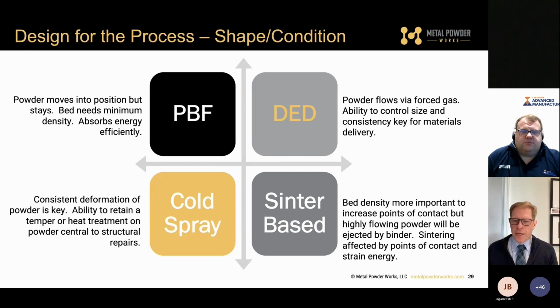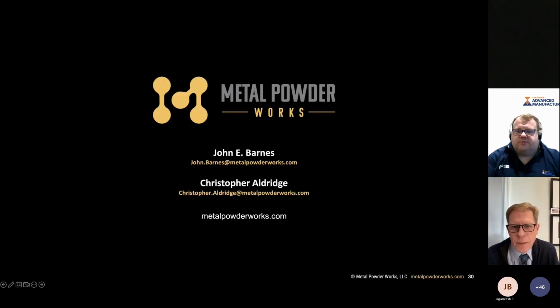And then I call it sinter-based rather than specifically binder jetting. So, any of the technologies that derive their density from sintering, having multiple points of contact is desirable. Our process, because we mechanically drive the powder, we have high strain energy surfaces. Theoretically, those should give you a lower sintering temperature. So there's hope that having multiple points of contact creates multiple sintering initiation points. And that's what I have for you.